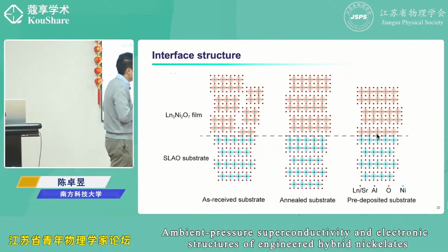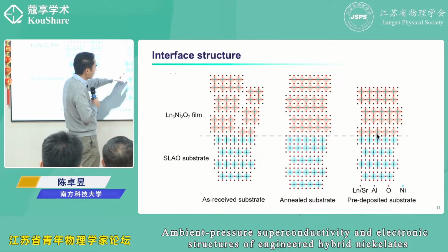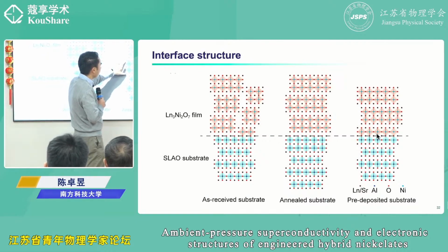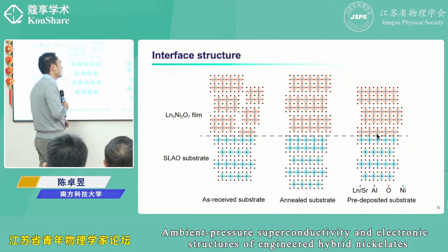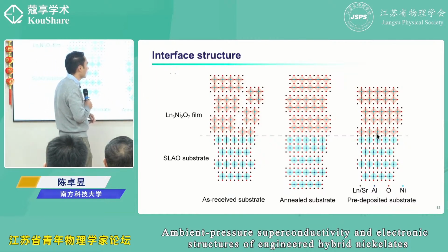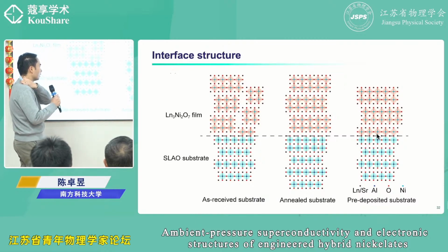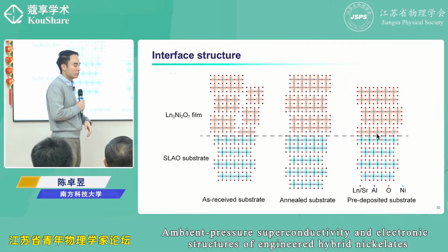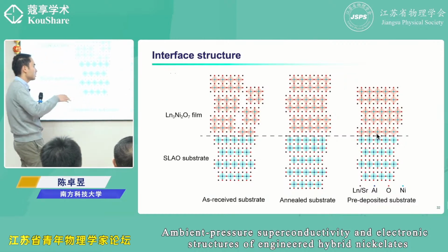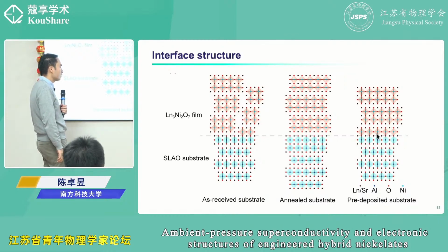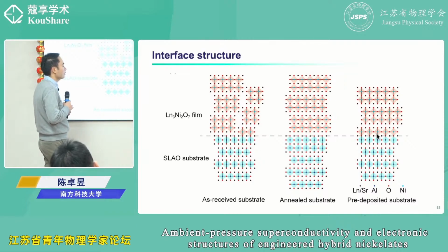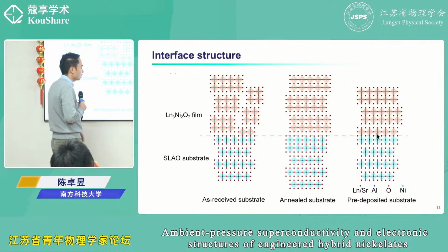A way is to anneal the substrate. If you anneal the substrate, it will automatically form a bilayer of aluminate at the surface of the substrate, and then you grow bilayer nickelate on top. It's pretty coherent. This is the method that we used for our first report. But the productivity is pretty low because the quality of the annealed substrate is not so consistent. I think only about several tens of annealed substrates are good enough quality, so the productivity is very low.